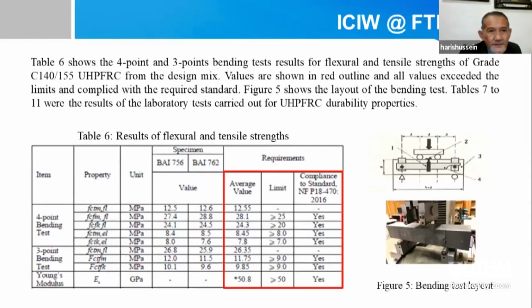Table 6 shows the result of the 4-point and 3-point bending tests for flexural and tensile strength for grade C140/155. Values are shown in red outline, and all values exceed the limits and comply with the required standard. Figure 5 shows the layout of the bending test which was carried out for the purpose of verifying the grade C140/155.